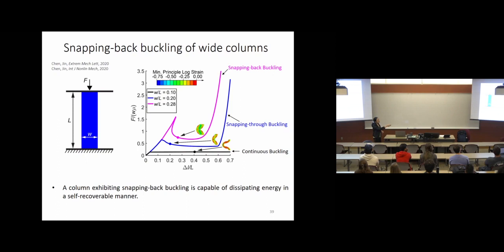But now if you increase the width to length ratio, you actually observe this so-called snap-through buckling, which means after the buckling point, the force will decrease with a further increase of displacement. But recently we discovered that if you further increase the width to length ratio, which means a very wide beam, we observe this snapping back buckling, which means after the buckling point, if you follow the equilibrium curve, both the force and displacement actually decrease, but with the slope still remaining positive.